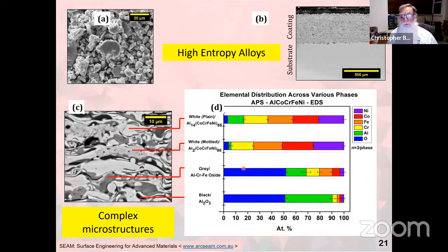Another example is high entropy alloys in collaboration with the Indian Institute of Technology in Madras. We start off with the powder, which we make in the lab, 5 elements all mixed together, approximately the same molar content. We spray a coating in the lab. We look at the cross section and wow, look at this chemistry. This has got a lot of phases in it. You can just tell by looking at it.